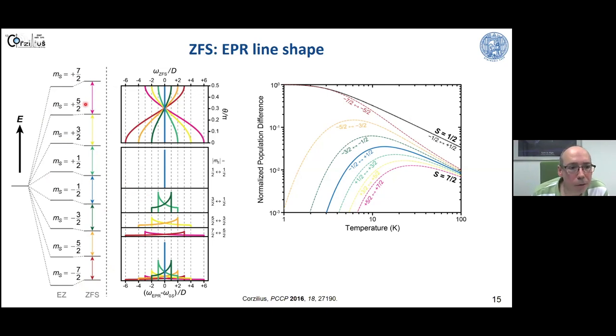And this means that if we go below a certain threshold, it's not like in the S = 1/2 case where we always have our population in the ground state, which is practically connected to our accessible EPR transition. In high spin systems, we populate a satellite transition and we depopulate our central transition. So we put practically all the polarization into, for example, this dark red transition, which is very broad, and we cannot really access this and use that for DNP, and our central transition will be completely depopulated. And this already happens at moderate temperatures of around 20, 25 Kelvin, at typical fields of 9.4 Tesla.